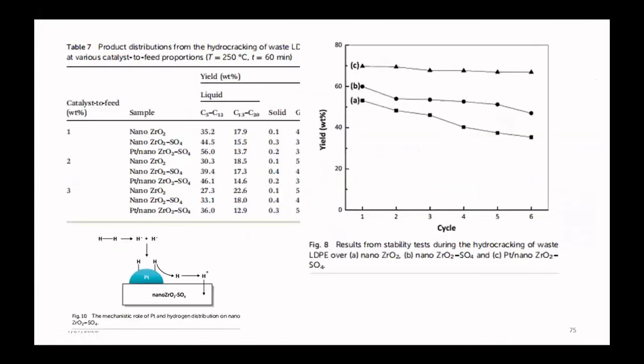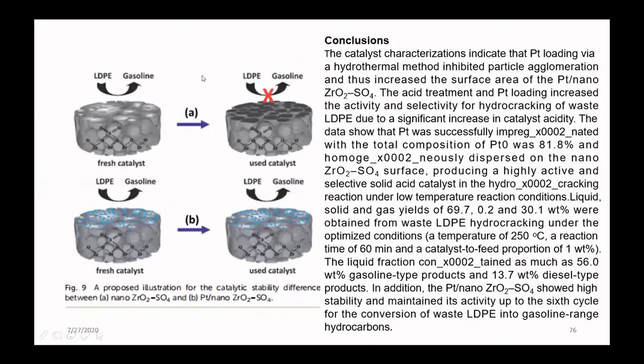This is the stability of the structure. After six cycles of the process, if you use platinum on nano zirconia, it is a relatively stable structure, in terms of the activity of the catalyst. But without platinum, there is a decrease in the activity of the catalyst. In conclusion, another example for the biogasoline process is the synthesis of chromium alumina bentonite composite for hydrocracking catalysis of castor oil. We use another material, a nanocomposite.